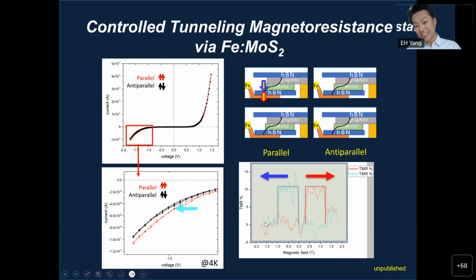Then you increase the magnetic field, basically decreasing the negative value there. And what happens as you increase the value? Something flips. What? This soft magnet flips. As it flips, you have the higher resistance, therefore tunneling magnetic resistance is shown. Then you further increase, and even the hard magnet flips. Therefore, it lowers the tunneling magnetic resistance. Then you go all the way, and you start going in reverse in the magnetic field. You now decrease the magnetic field, and it will flip the soft magnet again, and it will give this higher tunneling magnetic resistance here.